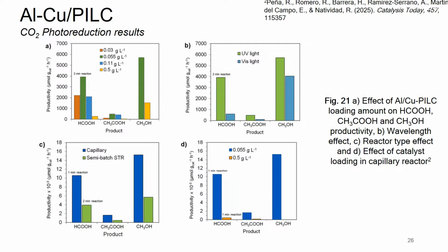And with aluminum copper pillar clay, look here, the low catalyst concentrations that we use with this catalyst. The best catalyst loading, the best in terms of formic acid production, was 0.05 grams per liter compared to the 1 gram per liter that we use with copper over titanium dioxide. And you can see here the productivity of formic acid, acetic acid, and methanol.